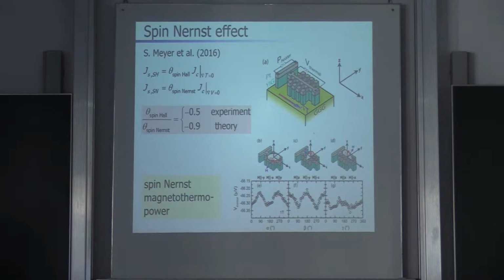Now, what's the spin-Nernst effect? It is by definition defined like that. So this one would be the charge current, which is driven by a voltage difference, assuming that the temperatures are constant. Now, if you drive a charge current through the system purely thermoelectrically, by a temperature gradient, then you also get a charge current, and this charge current also generates a transverse spin current. And this coefficient is called the spin-Nernst angle.